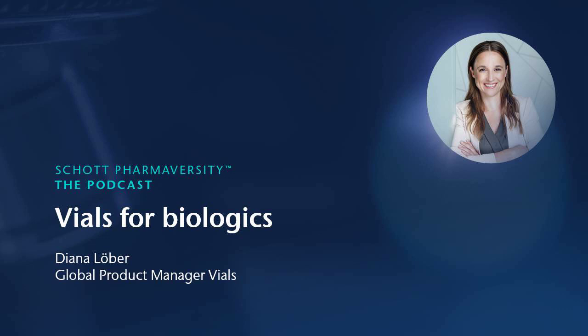And these behaviors lead to the situation that the crimp might not be able to hold the CCI because it might not be able to compensate for a gap between a brittle, shrunk stopper and a vial that almost didn't change. And this is why we perform tests at minus 80 degrees Celsius that I've shown in the Pharmaversity session. Yeah, indeed, thanks for that. Can you provide, Diana, an overview of what other relevant topics shall be considered?